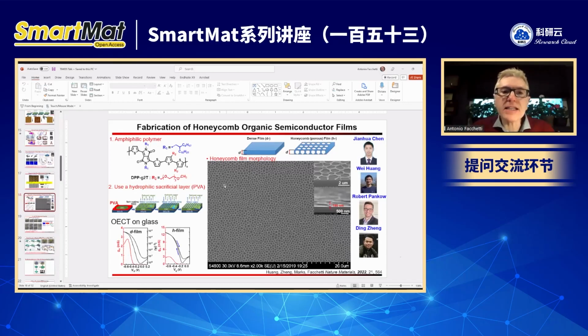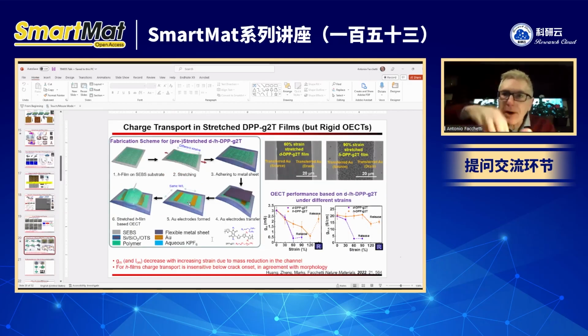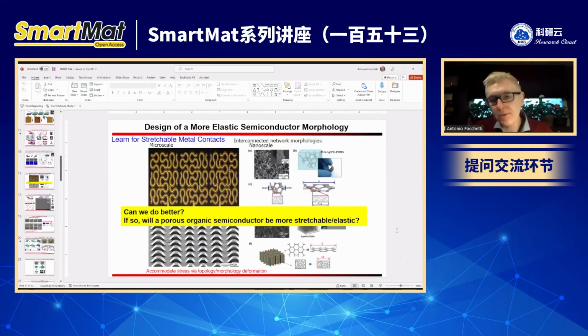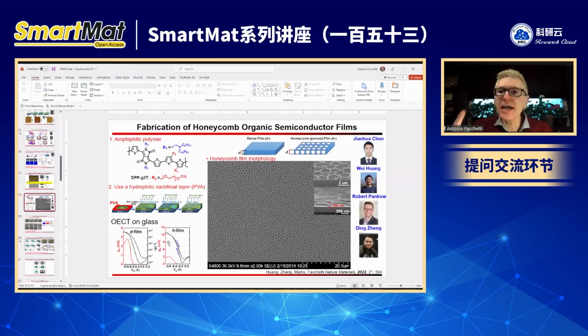Yes. And in fact, in order to make the device, when you make the film here, you dip the substrate in water, the PVA dissolves, so this film floats in water. So you can take the film and transfer it to make these devices. In all the devices I show, the honeycomb is not prepared directly on the OECT, but prepared on another substrate. It floats in water, and then we pick up the film and transfer it. This is how we make these devices. So PVA has two functions: sacrificial layer and making a good honeycomb. Yeah, this is very important.